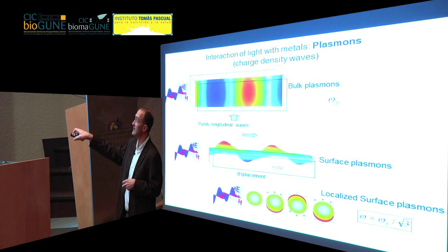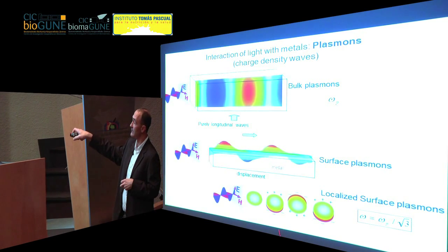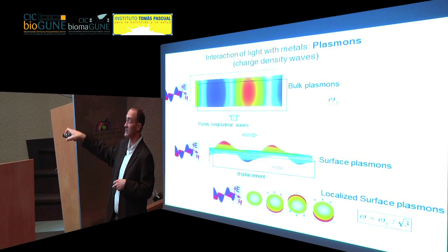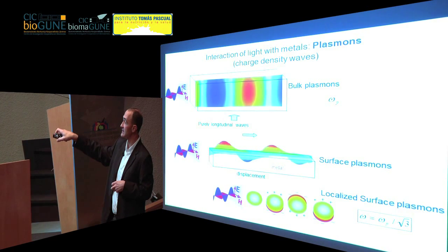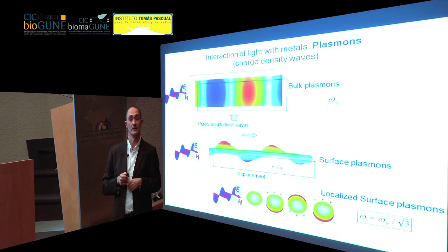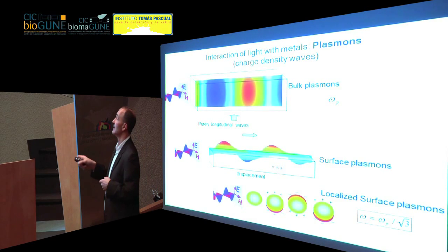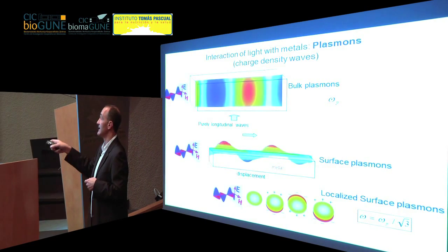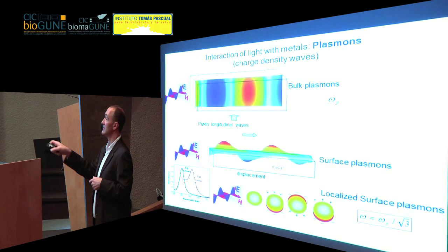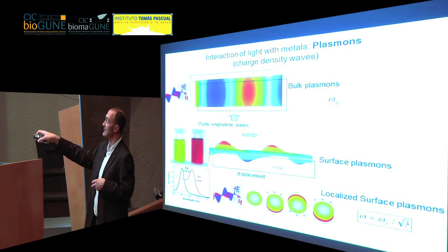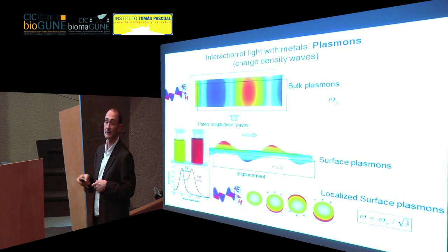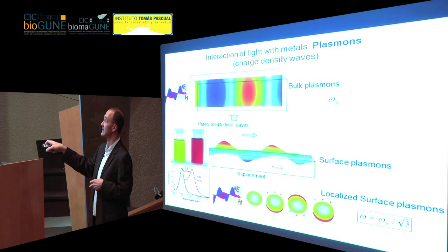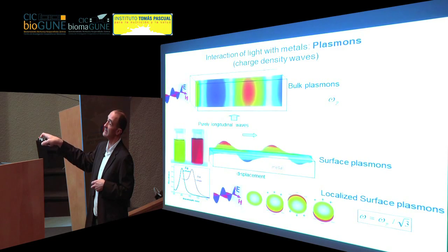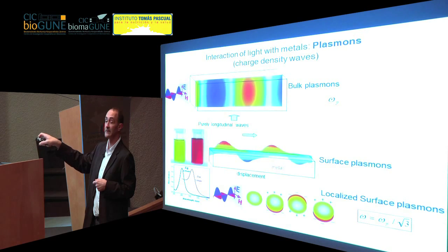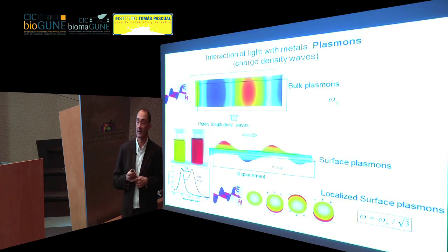So here what you have in very tiny particles is that you form a dipole, and then there is an oscillation of the charges of the dipole in resonance with the wavelength or the frequency of the light that is shining on it. So this is what defines these nice colors that I was showing you before. So for gold, you see that the main absorption is around 520 nanometers for spherical small particles. For silver, the absorption is, well, depending on the conditions, around 400 nanometers. And this is why colloidal silver is yellow, colloidal gold is red.